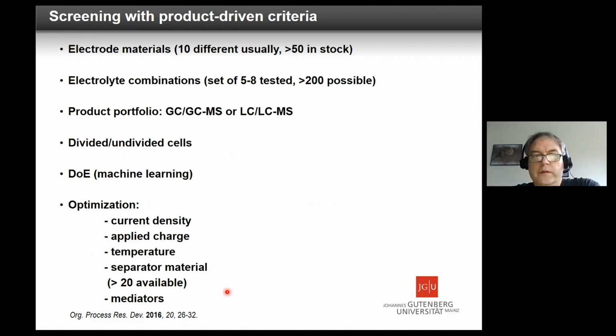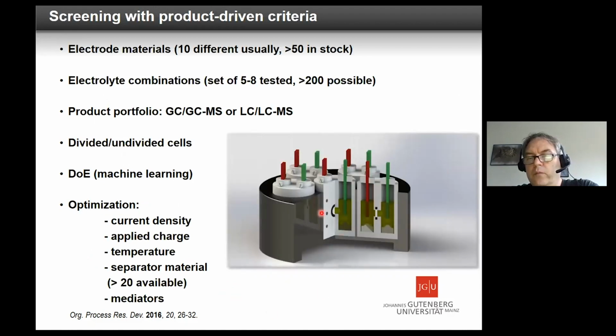Therefore, we early started to do a screening with product-driven criteria. And this is a compromise to make enough electrolyses on one magnetic stirrer, but in a good, accurate way, because here the dimensions are very clear. You can even use that later on for optimization, because in a more advanced screening technology, you don't need only yes or no, you need precise data. And therefore, we start here. We have 10 different electrodes. We usually start with those. We have more than 50 now in stock.